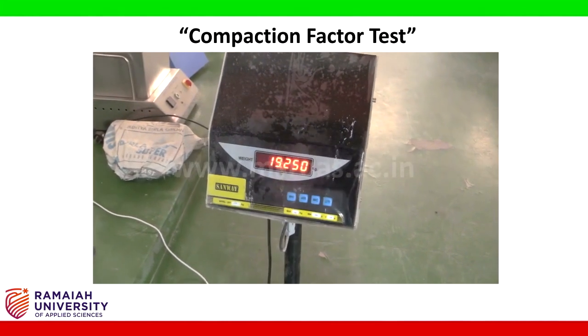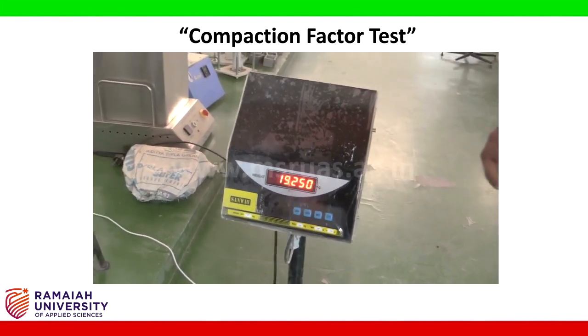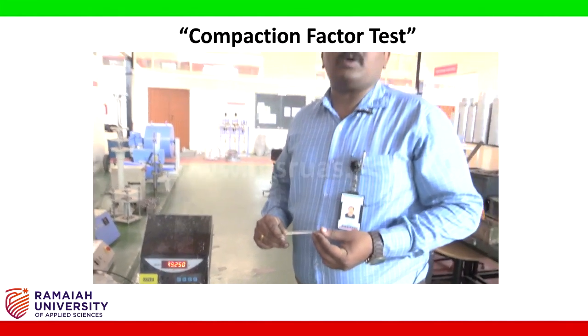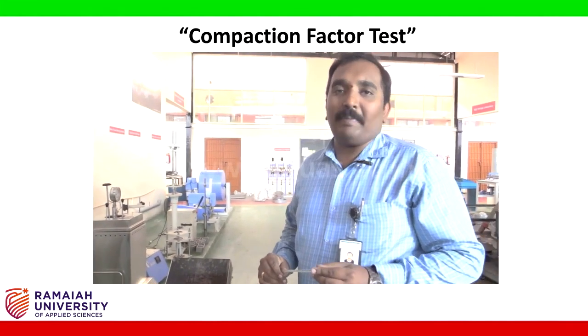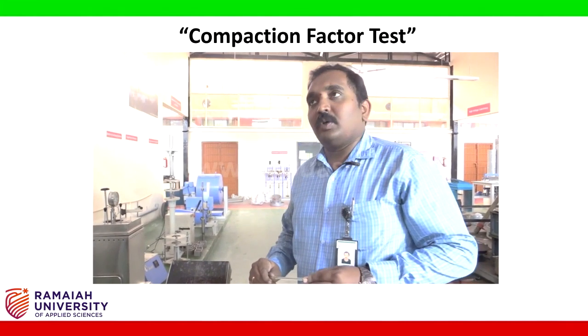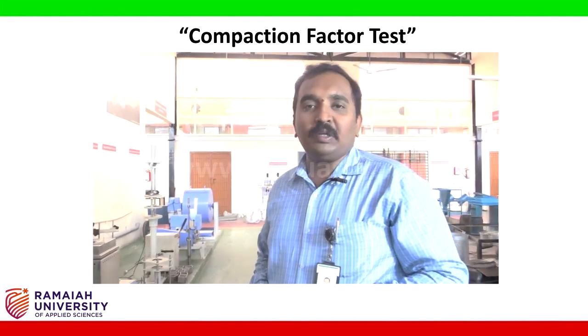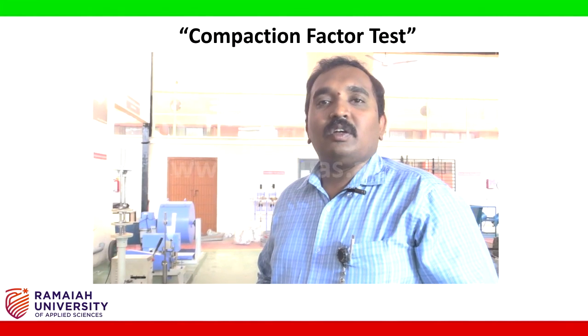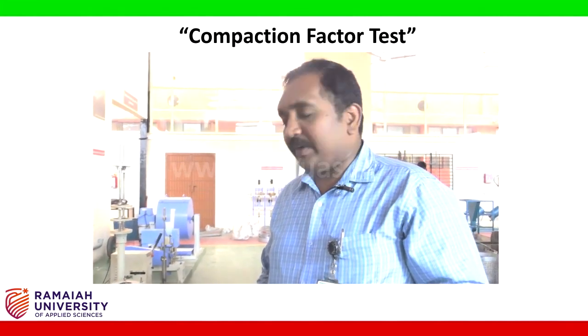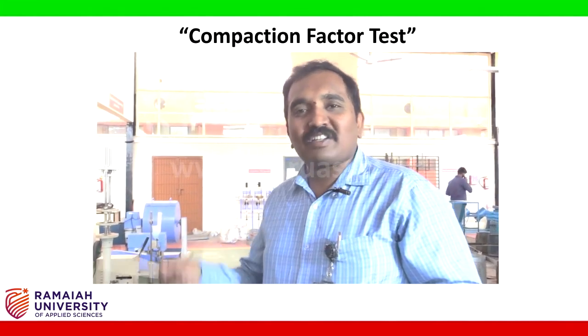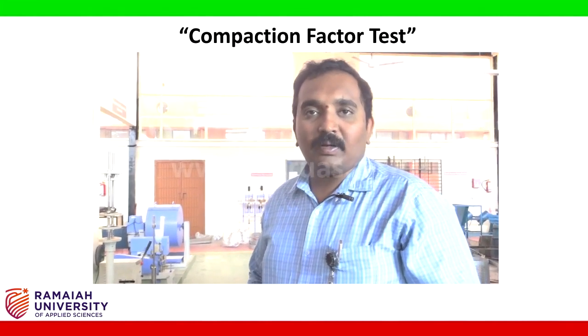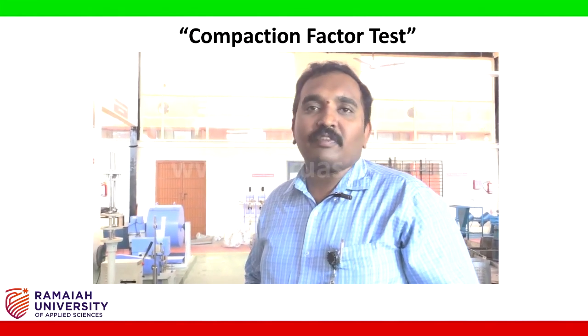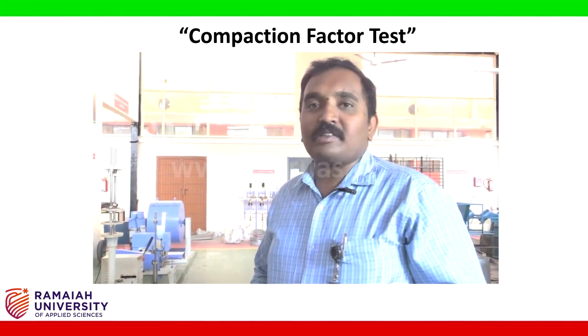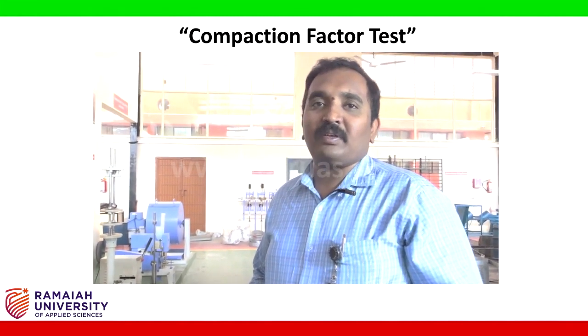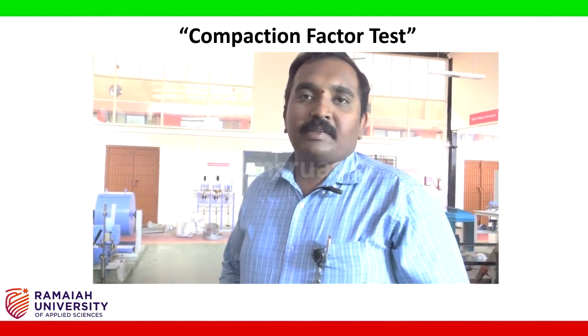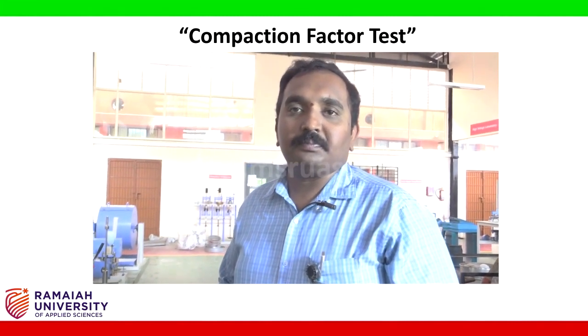The ratio of the weight of partially compacted concrete to the fully compacted concrete, we call the compaction factor. You can get a compaction factor value from 0.7 to 1. A value of 1 indicates that your theoretical compaction, your practical compaction and the compaction from the free fall are equal. That generally happens for self-compacting concrete. For other mixes, you will get a value less than 1. This completes the compaction factor test.